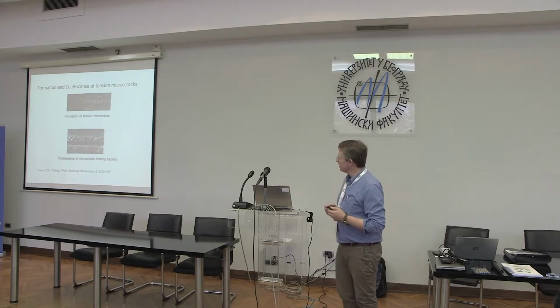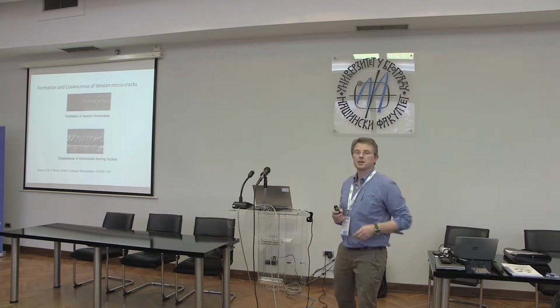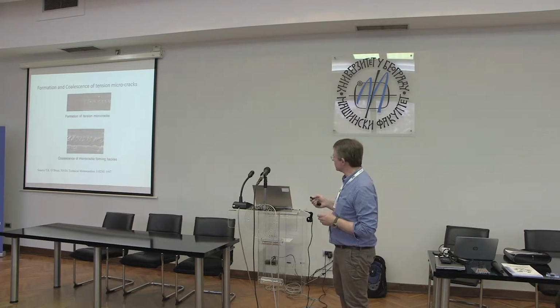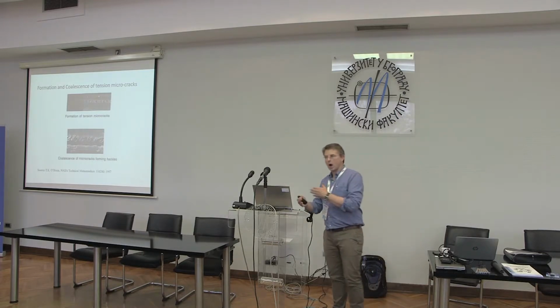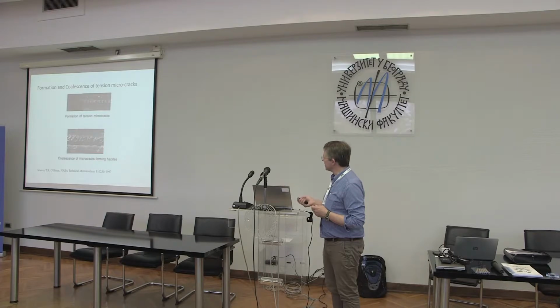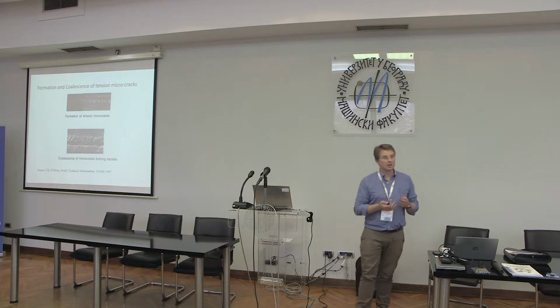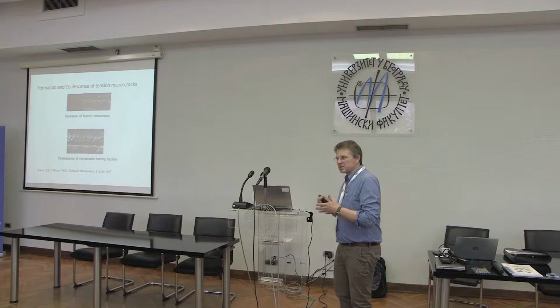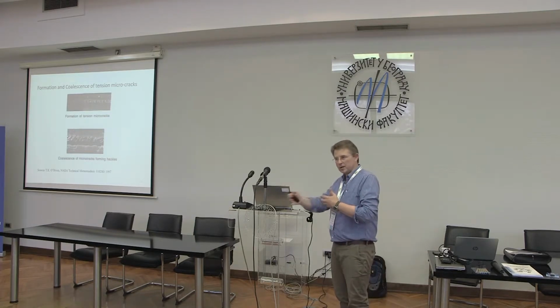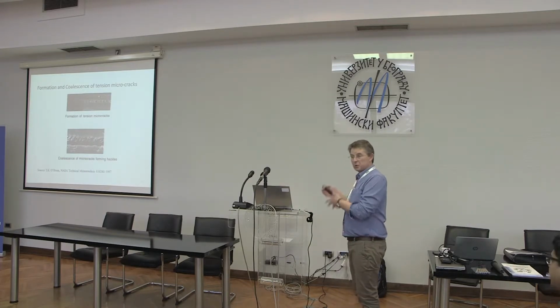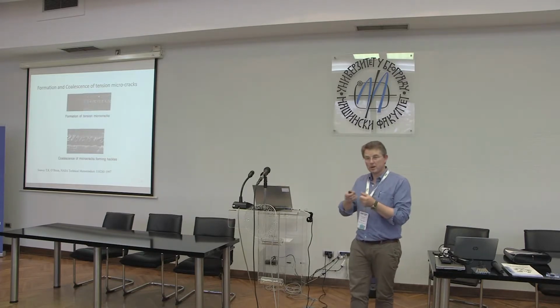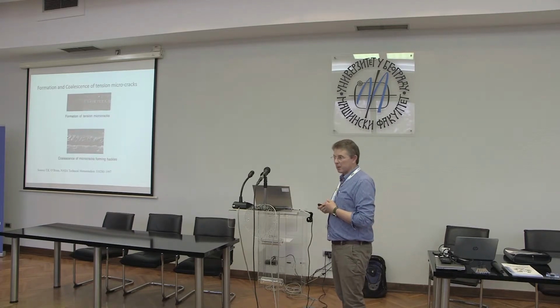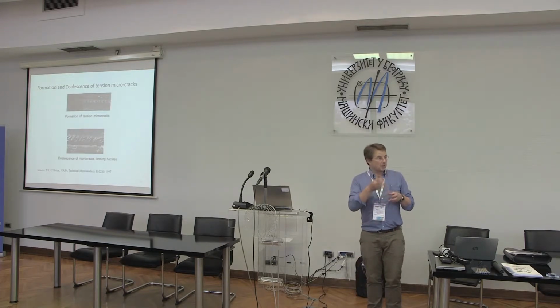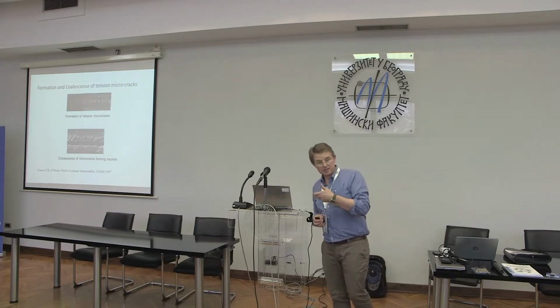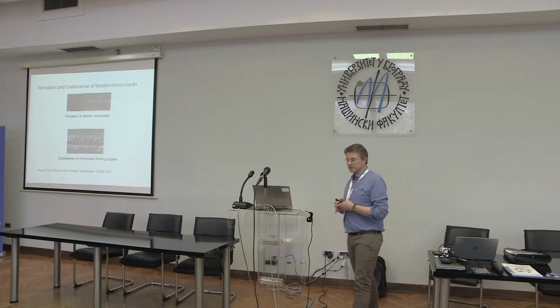And of course, if you look at the micromechanics of what's happening at the crack tip, we looked at some inclined microcracks in an earlier slide, but here you can see the idea that you can have a head of a shear crack, you can have these extended microcracks extending into the material. So formation of tensile microcracks, and of course what then can happen is that the material in between the microcracks can shear yield. So there's almost an analogy to the crazing mechanism of a polymer, where you can have lots of voids and you can have material forming fibrils in between. Of course, we're talking epoxy here, so we're not talking about crazing, we're not talking about fibrils, but we're just talking about shear failure of ligaments of material in between microcracks. And it's widely believed that it's this extra energy dissipation by the failure of these little shear ligaments that is causing the large increase in the fracture resistance.